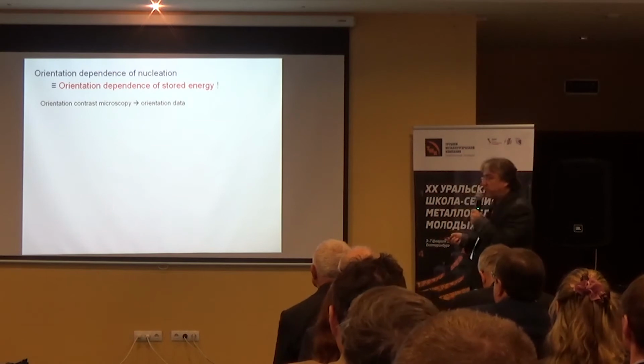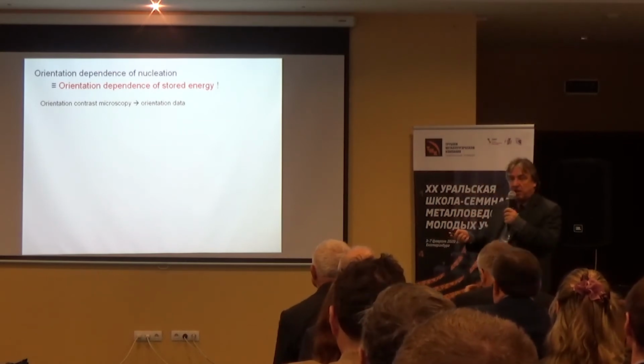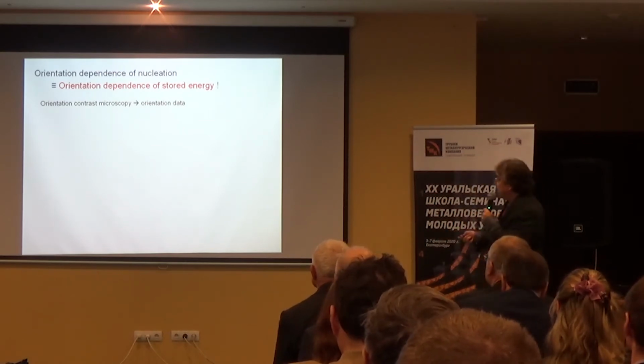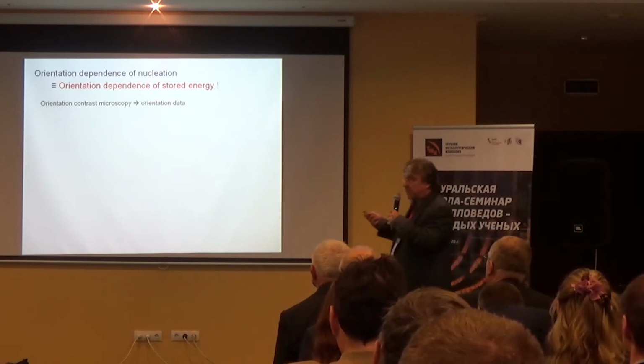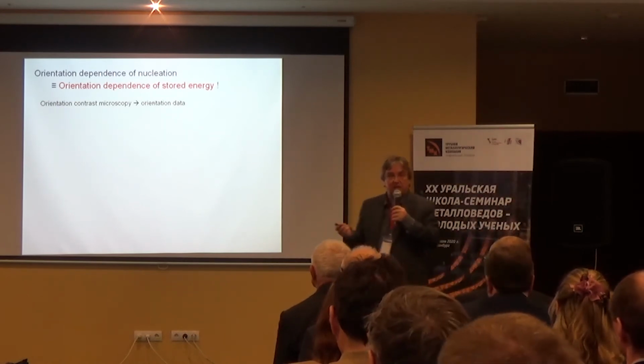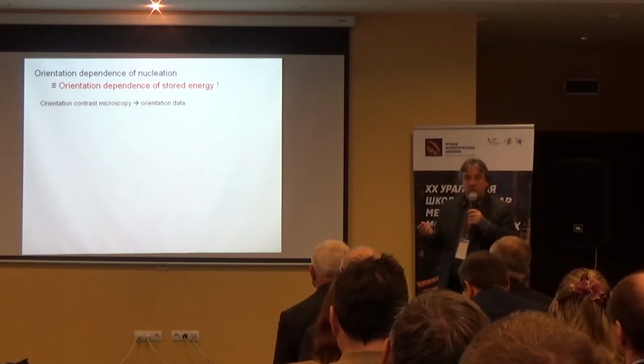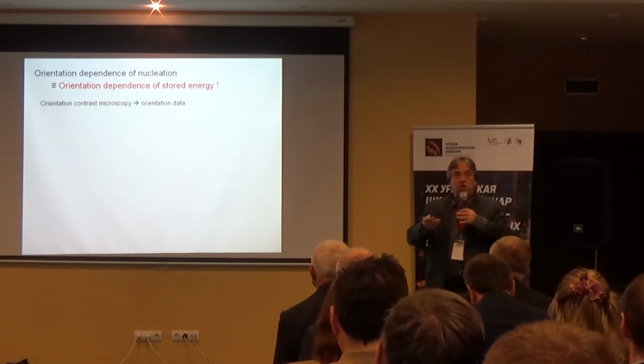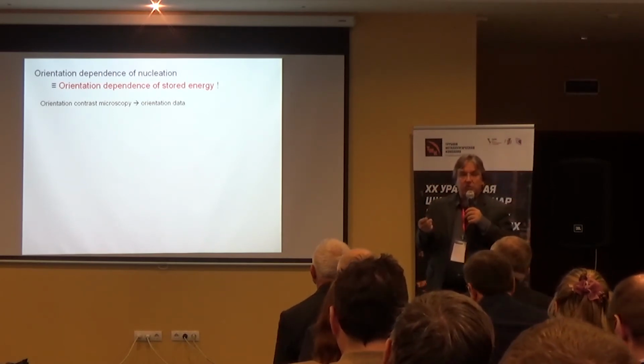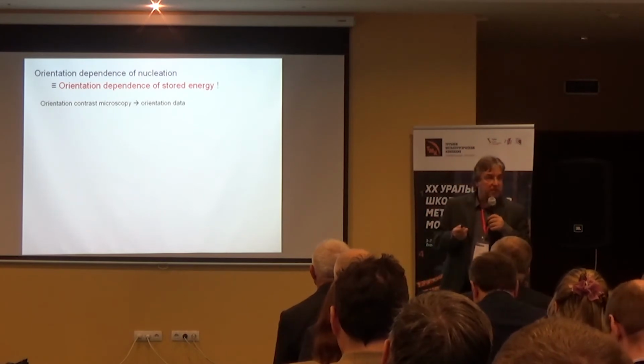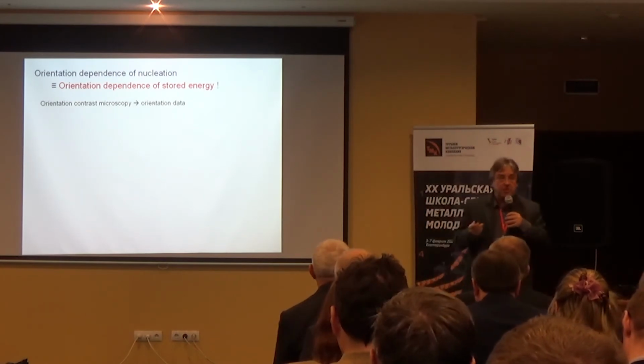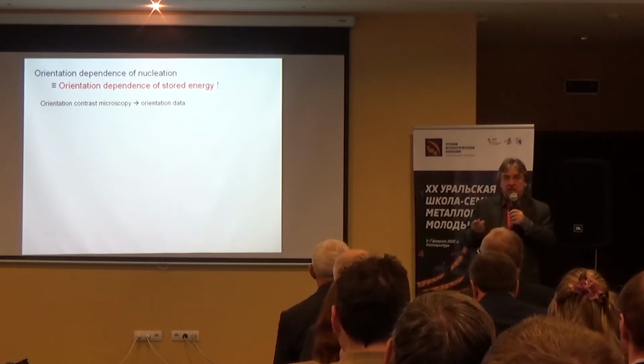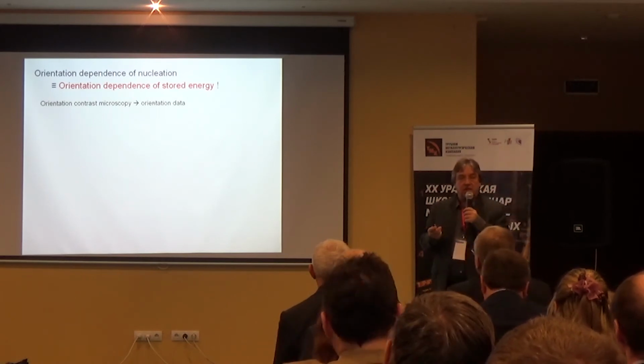So this, for example, can be visualized by orientation contrast microscopy. You know the EBSD, we can collect orientation data on the local scale with resolution of scanning electron microscopy. Let's say EBSD, typical, the highest resolution you can get is 10-20 nanometer.